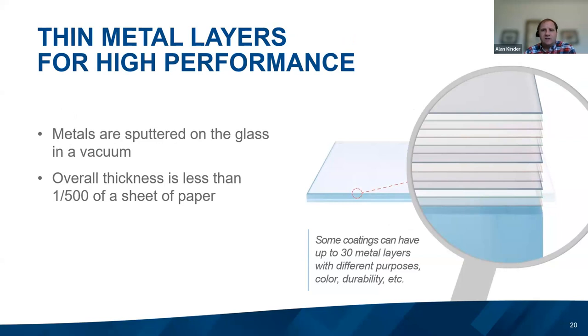So you take these big stock sheets of glass, you ship them over to the Low-E coating line, you put them back on through robotics, and then it goes through a very intensive washing and drying process. We mentioned we're raining metal onto that glass face, or sputtering metal onto that glass face. So we don't want to have any silica sand, oil droplets, water droplets, anything that might keep that coating from adhering to that glass face. That could lead to defects by way of pinholes or the coating not adhering to the glass substrate.